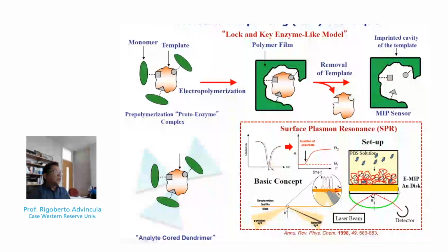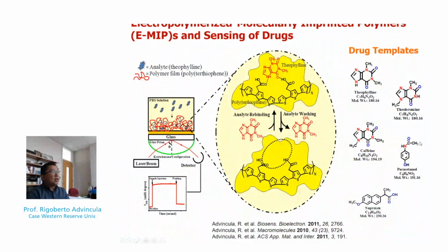So using the surface as a working electrode to electropolymerize the deposition of this complex, we use electrochemistry to get a very controlled dielectric film, we then use SPR to monitor the binding kinetics or assay of the original analyte or competitive analyte on the surface. So in other words, we created our own sensing element using the MIP approach. One of the first papers we published was the detection of caffeine, theobromine, theophylline. Again, using this concept where we electrodeposit the complex of the monomer and the analyte, we deposited it on the gold side of the SPR, and then finally we did the chemistry.